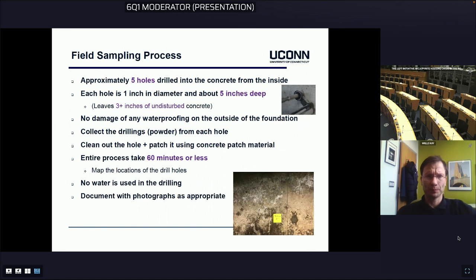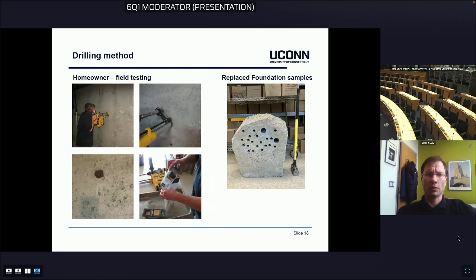Next slide. This is what the drilling process looks like, and we also get larger chunks of concrete into the lab, where I can investigate the statistical variation by drilling more holes. For example, you see the 1 inch diameter holes, the smaller ones, and in the lab we also core larger ones, but this is not what we do with the homeowners.